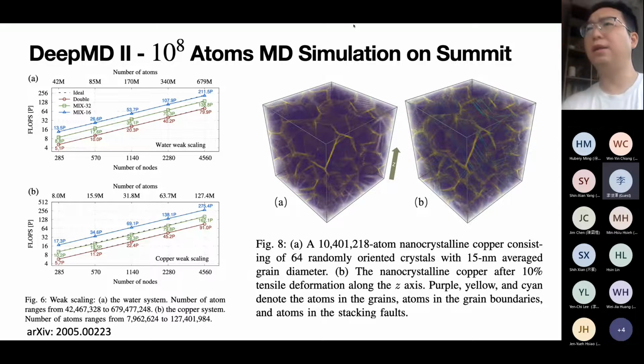The one in dark green on the right-hand side, if you can see there, has a couple of stripes running through along the diagonal. I hope you can see that. It's kind of cool. By simulating 100 million copper atoms, they are able to simulate a pretty big 15 nanometer nanocrystalline grain, which is decent size, and they are able to see structural faults, which allow us to study material properties: stress, strain, tensile, whatever. So that's the order of magnitude that we need for this structural simulation.